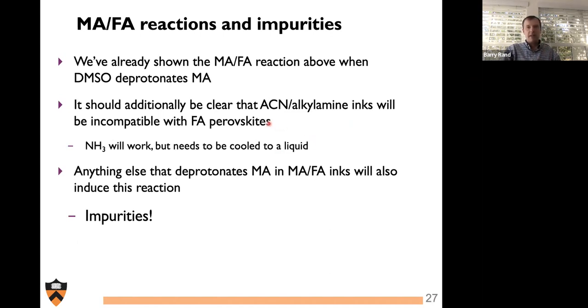And also the situation with this acetonitrile alkylamine ink, it should be pretty clear that that will be incompatible with formamidinium perovskites because you'll have this instantaneous reaction. It's viable that ammonia can work, but this will only work when you've cooled ammonia down to be a liquid. And so it's not abundantly clear whether that's a completely pragmatic and realistic approach. We also find that anything else that deprotonates methylammonium in these inks will also induce this reaction. And just published by Joe and Ross, impurities can also act in a similar manner as DMSO does.